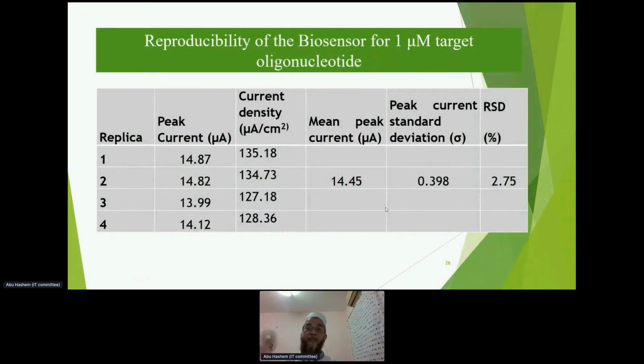Reproducibility of the biosensor. Good reproducibility of the biosensor was observed with peak current at 14.45 and relative standard deviation of 2.75.